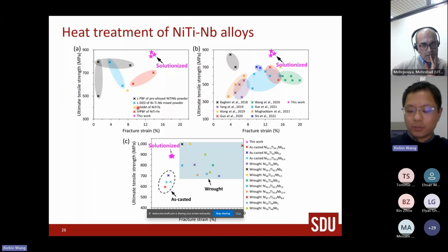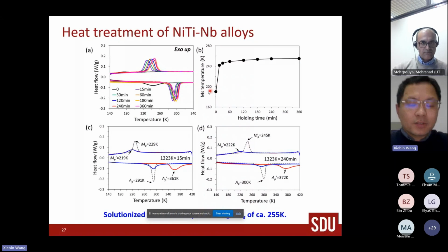But after solution treatment, we compared the mechanical property with other alloys, and it's good as compared with the additive manufactured parts, but it's lower than the wrought parts. After solution treatment, the transformation temperature increases to a high value, and this is not what we want for nickel-titanium-niobium ternary alloys.